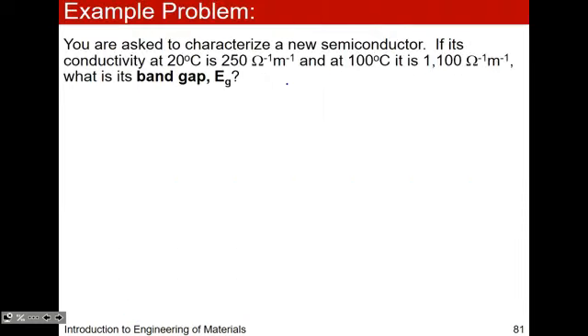So let's do that. If you're a new processing engineer, you're part of R&D at Intel, one of the thousands of people out in Oregon, all right, and Arizona, possibly now New Mexico, and you're asked to characterize a new semiconductor. You've measured at room temperature the conductivity, which is 250 inverse ohm meters. Room temperature here is 20 degrees Celsius. And then you also measured at 100 degrees Celsius, because you just ramped up the temperature. You measured the conductivity to be 1,100 inverse ohm meters. So how do you backtrack out this band gap?